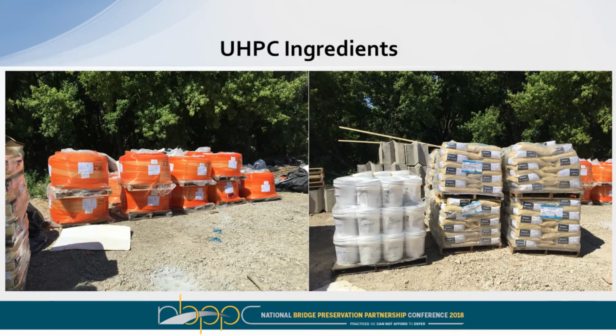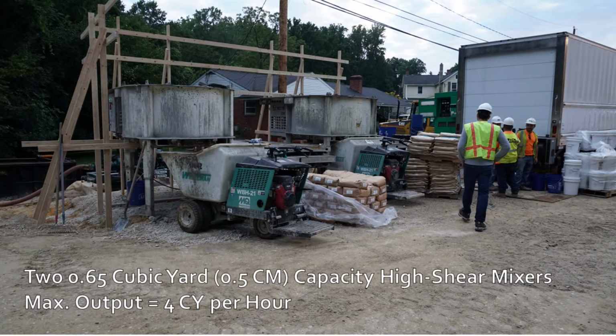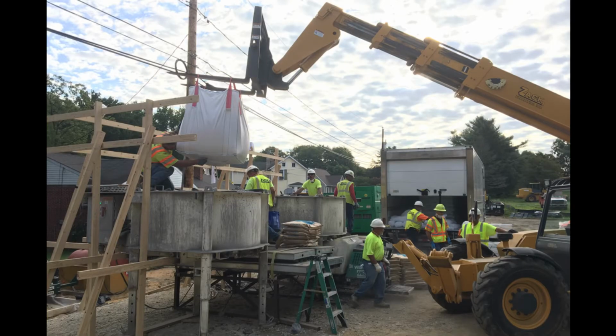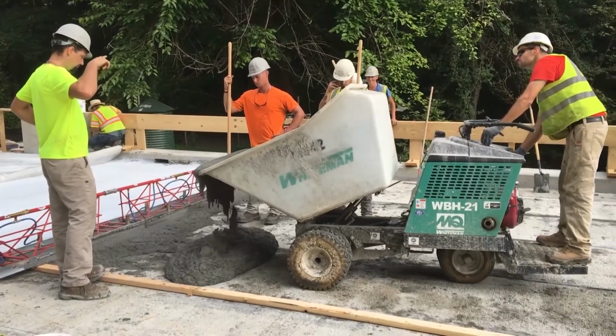And on this job, since it was a small enough project, we provided materials in bagged form. So on the left, you see the pre-bagged premix. And then on the right are bags of steel fibers and tubs of superplasticizing admixture. And we had these smaller pan mixers. Each one can mix about 2/3 of a yard per batch, and we have 2 of them working in tandem. We can do about 3 batches per hour to give us an output capacity of about 4 cubic yards per hour there. And there's a guy loading the bag in the mixer here, and then another video of them placing it on the bridge deck itself.